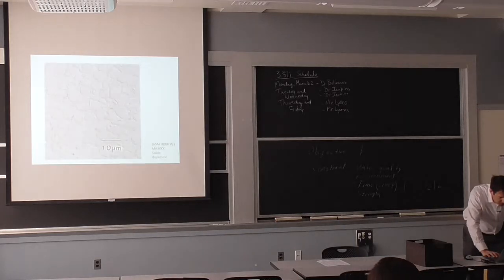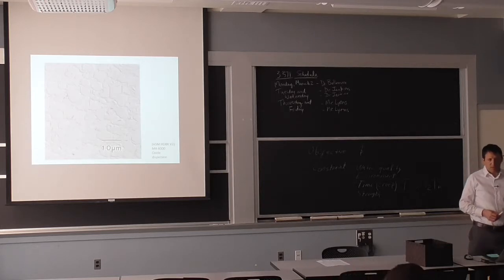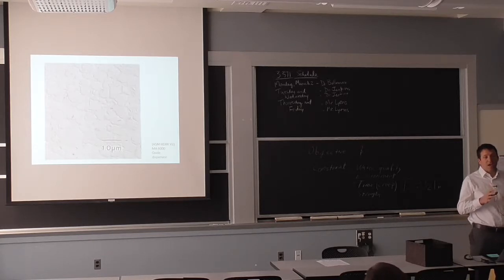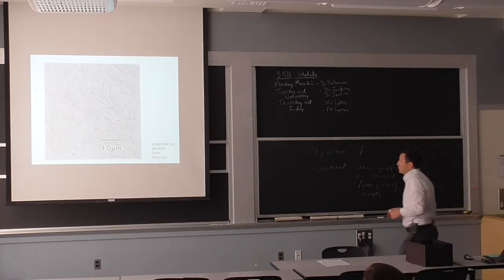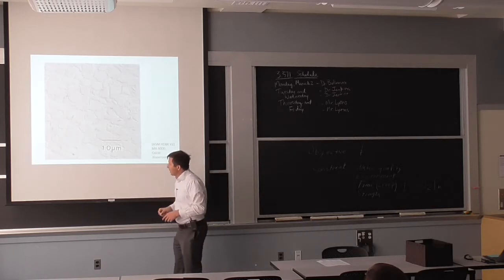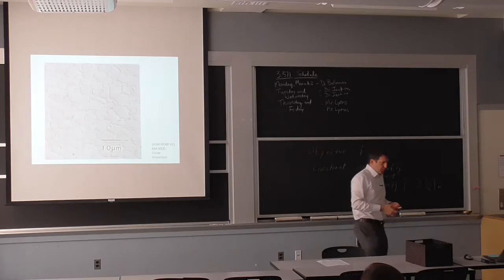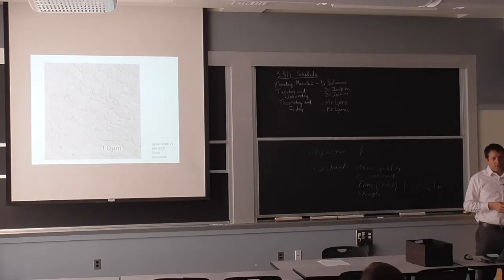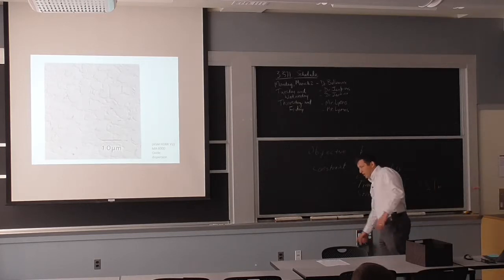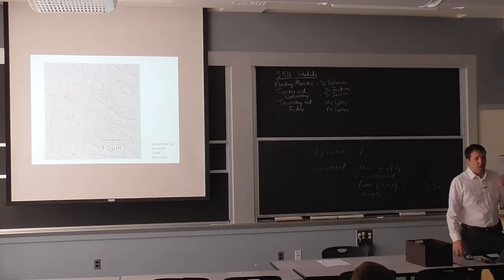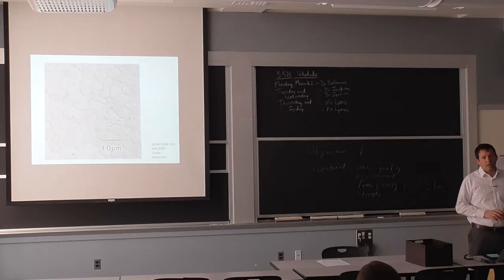Now, there's a little bit too much detail here in terms of the different creep behaviors. So let's just say that because I was giving the example of the turbine blade, it's a big single crystal in the most demanding application, but it has a lot of second phase in it. So if you look at this structure, you have second phase in the matrix. Sometimes it can be up to 50, 60 volume percent, and that is all to slow down the movement of these dislocations we talked about on Monday. So it's a very, very specific case in terms of design, but at the same time, technologically, it's very interesting because all these concepts we talked about come into play here in terms of trying to limit the movement of the dislocation, in this case, to avoid the creep behavior.